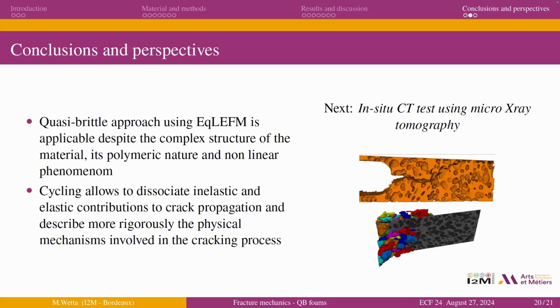So to conclude this presentation, we can say that for this complex material, even if we have a complex microstructure, polymeric nature and a nonlinear phenomenon, the quasi-brittle approach seems to be relevant for describing the fracture behavior and the crack growth resistance. Another conclusion concerns the cyclic loading, which seems to be interesting to dissociate inelastic and elastic contributions, and helps to describe more rigorously the physical mechanisms involved in the cracking process. The next work, which is still in progress, is to try to understand the role of the cells in the cracking process. For that, we have made some in situ X-ray tomography fracture tests. Thanks a lot for listening.